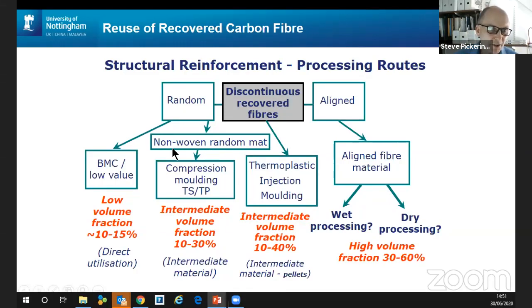You could turn the material into a non-woven mat by using paper making type processes, and you could use compression molding to produce intermediate volume fraction, say 10 to 30%. So again, the higher value materials here. But carbon fibers are usually used in very high fiber volume fraction applications where they get up to 60% fiber volume fraction, and it's difficult to achieve that with random processes, as I'll explain in a few minutes. So if you want to get to the high fiber volume fractions, you really need to align the fibers in some way so you can pack them together.